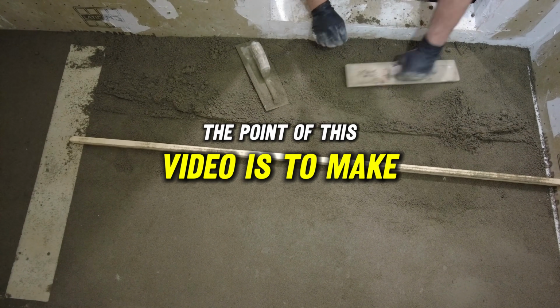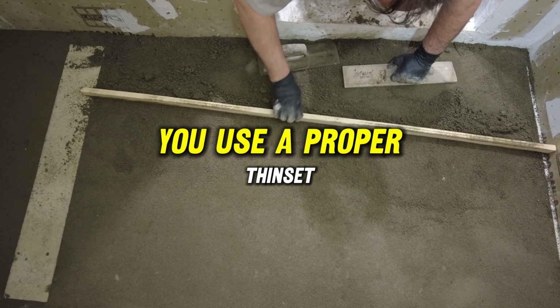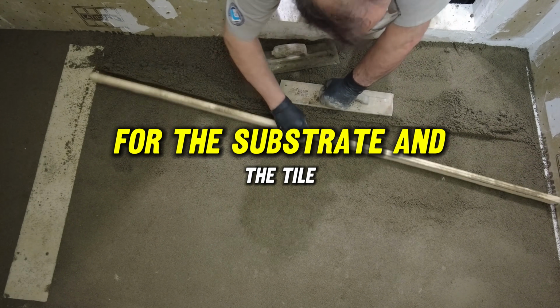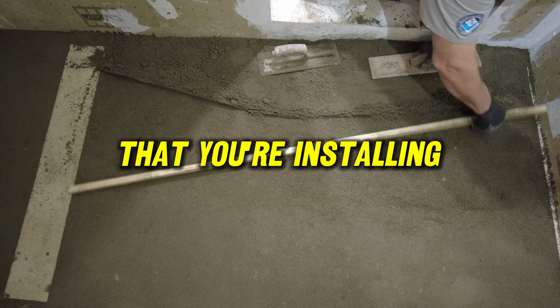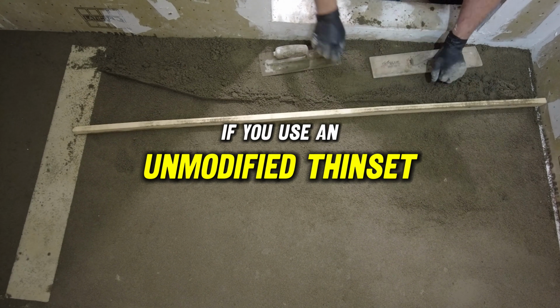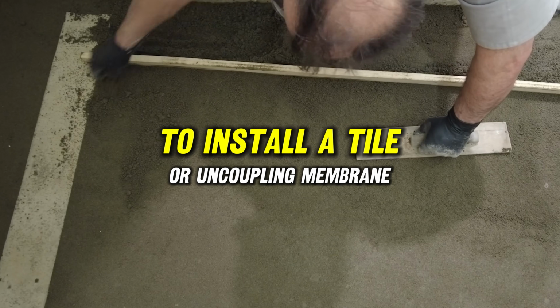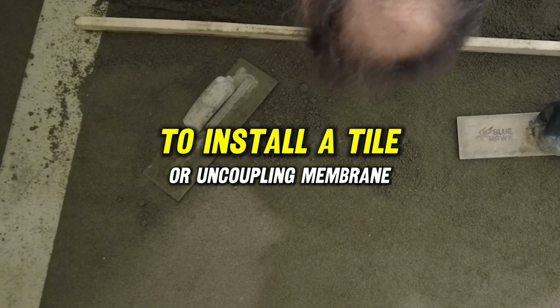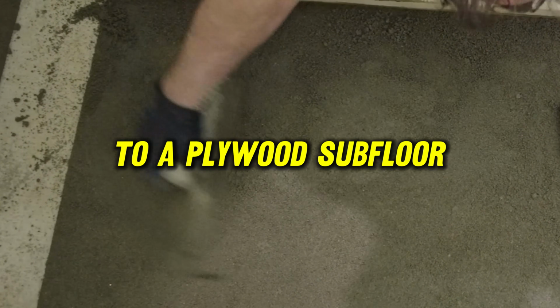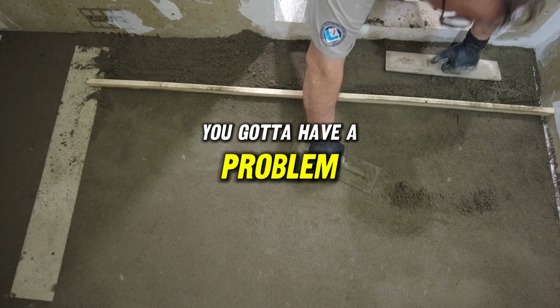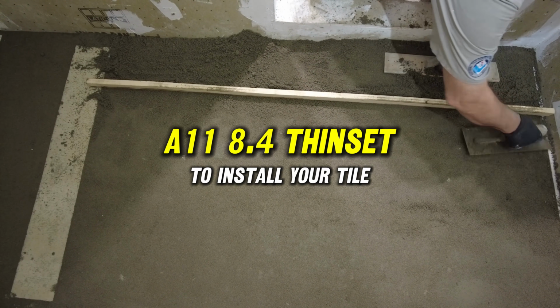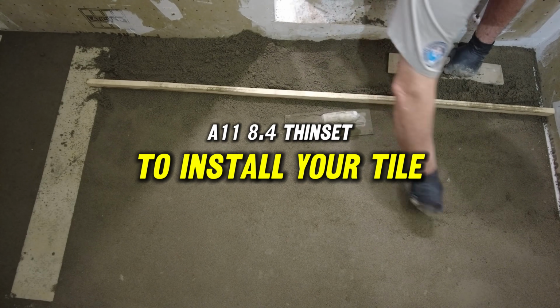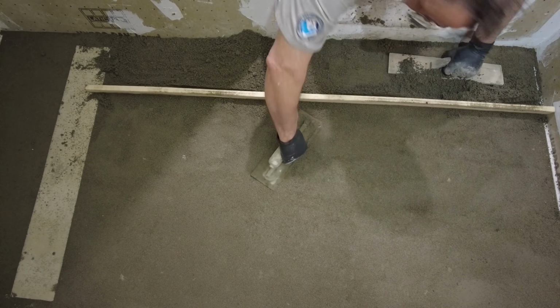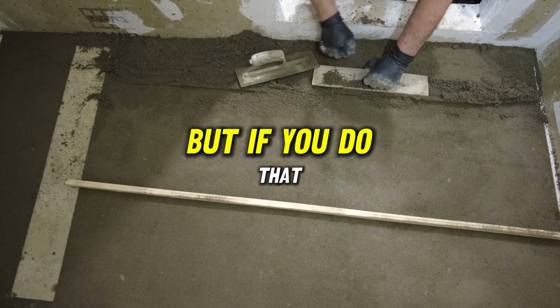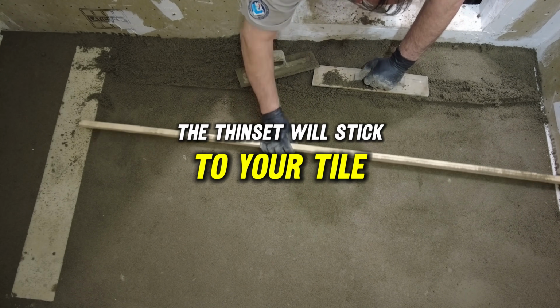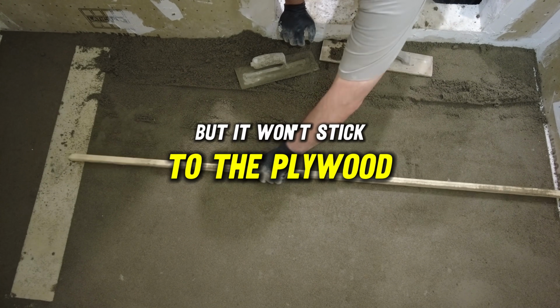The point of this video is to make sure you use the proper thinset for the substrate and the tile that you're installing. If you use an unmodified thinset to install a tile or an uncoupling membrane to a plywood subfloor, you're going to have a problem. If you use A118.4 thinset to install your tile directly to plywood, the thinset will stick to your tile, but it won't stick to the plywood.